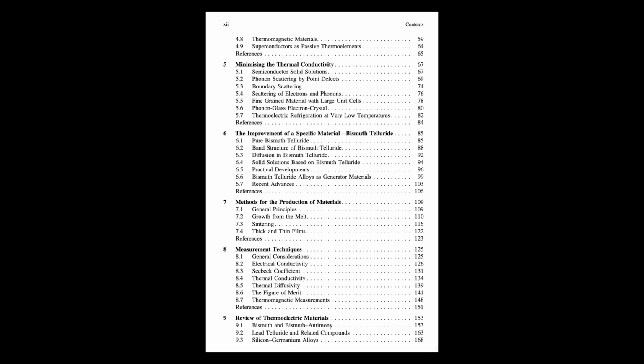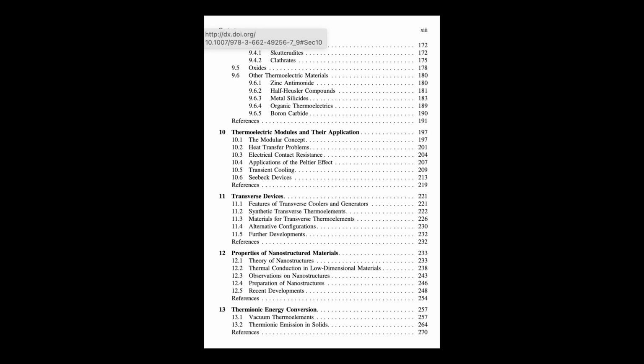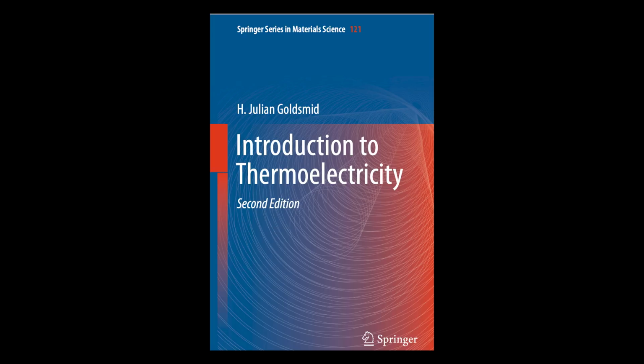Nice analogy. What about scattering from point defects? What kind of tiny flaws are we talking about? Point defects are just single atom scale imperfections. A missing atom, vacancy, an extra atom squeezed in, interstitial, or a wrong type of atom swapped in, substitutional impurity. These disrupt the perfect lattice rhythm, changing how it vibrates and scattering phonons. How well they scatter depends on the size difference and the mass difference compared to the host atoms, which causes strain and mass fluctuations. For phonons much bigger than the defect, it's like Rayleigh scattering, how the sky is blue, scattering light off tiny air molecules. Okay.